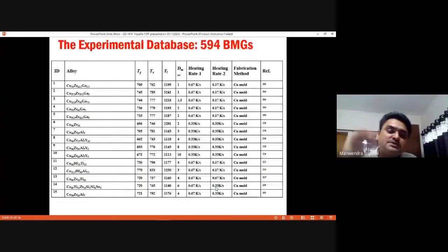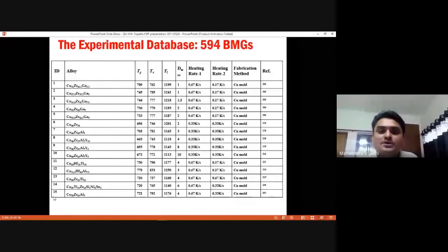Second, in this table I am showing you the data which I have collected. I am just showing you about 15 alloys, but I have data for 594 BMGs which are experimentally synthesized. For example, this is a 3-component alloy, this is a 2-component alloy, and this is a 6-component alloy, right? These are the compositions, which are experimentally synthesized, and this is the Tg value, which is less than the Tx, and this is the Tl, at which it is going to melt. At this temperature in kelvins it is going to crystallize, and below this it will be glass. And this is its maximum diameter. If you form metallic glass of this composition, it will be 1 mm or so. This is the critical diameter. And this is the heating rate employed while measuring Tg, Tx, Tl, and the fabrication method, copper mold based and other methods, and these are the references. So this is how we have compiled the data.